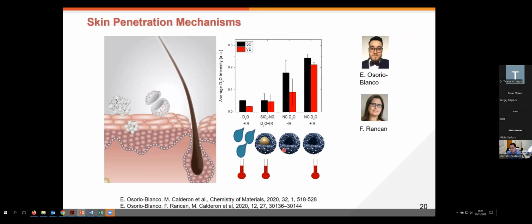Following this hypothesis, we compared systems with different architectures. For instance, in this case, we worked with nanogels, but now with a hollow core, so sort of capsules. We compare them with a hard core, and then we compare the penetration of just water into the skin. We analyzed this by Raman, and we could very nicely see that our nanocapsules, or nanogels, really increase the penetration of water in a very short time. And this penetration of water seems to be enhanced when we increase the temperature of the skin.